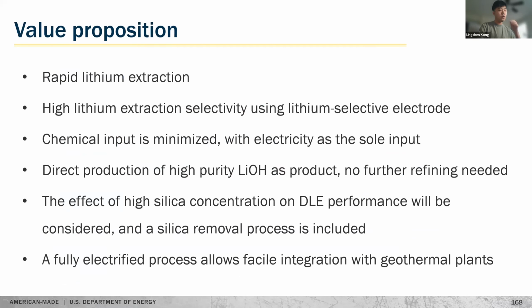The value and advantage of our technology and our total design is that we have a rapid lithium extraction compared to the traditional lithium extraction method. We have a high lithium extraction selectivity using a lithium selective electrode. We minimize the chemical input; there's almost no chemical, just water input. We have a high purity of lithium hydroxide as a product. And we have an electricity driven integrated setup for total lithium extraction. Next slide, please.